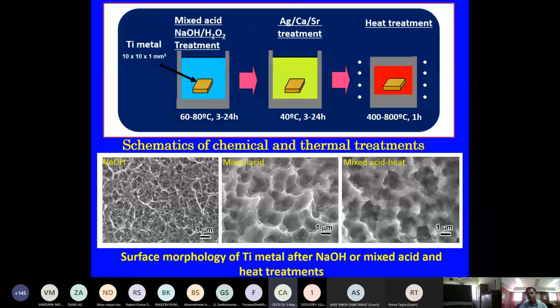In this process, in order to provide antimicrobial activity, we try to decorate or deposit silver nanoparticles over the surface, and we incorporate calcium and strontium ions in the surface. Because we are trying to develop a bone implant, calcium or strontium may accelerate faster bone formation or osteointegration ability on this metal surface.